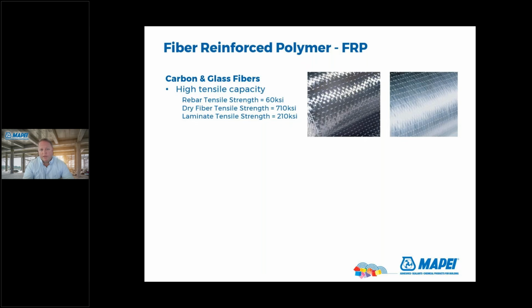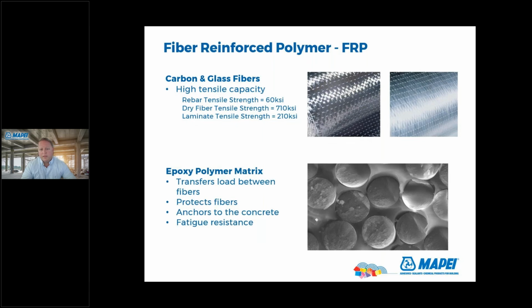So fiber reinforced polymer, it's a high strength fiber, carbon or glass. And just to compare these, a typical rebar in construction, you have about, say, 60 KSI. The dry fiber strength of these carbon fabrics is around 700 KSI, so about 10 times stronger. Now, unfortunately, there's no way to utilize the dry fiber in our projects. We actually have to get it wet with epoxy to adhere it to the structure. And so when you do that, it ends up lowering the strength, but it's still around 210 KSI. I just took an example of MAPEI's middle of the road carbon fabric. So significantly higher tensile strength than the steel.